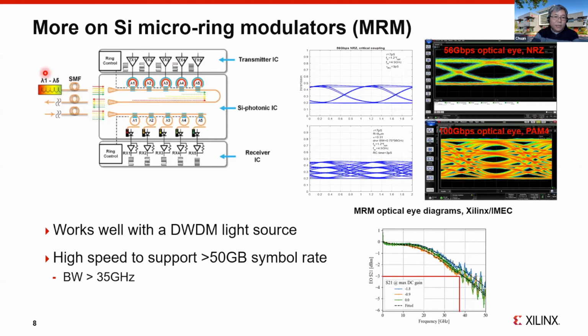So, assuming that you have a multi-line light source with evenly spaced optical channels coming in unmodulated. Since the ring modulators are resonance devices, if you tune different modulators to different laser lines, then you will modulate all these optical channels individually without having to demultiplex the laser channels. And on the receive side, you can also use ring-based optical filters to drop each individual optical signal to individual photodetectors and do the detection there. So it works well if you have a WDM light source.